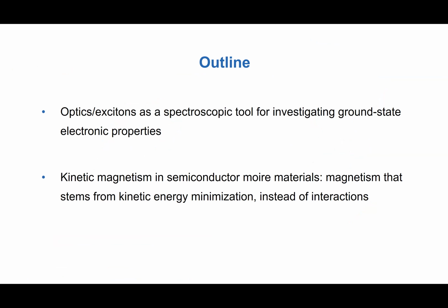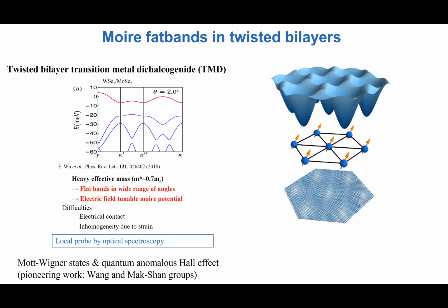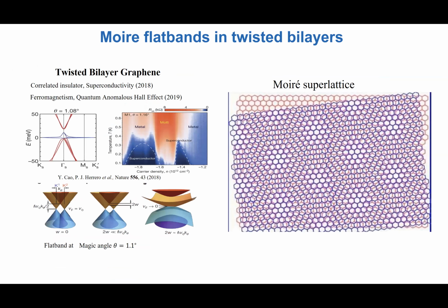Yes. Why is there no magic angle? Yeah, so basically, in the case of graphene, and there are experts here that can explain this much better than I do, but in the case of graphene, you start out with Dirac electrons, right? So this is as far away as you can get, in my opinion, from a flat band, right? So massless electrons. So what happens is that when you place two layers, and as they hybridize, they open up a gap, and the effect of this is to reduce the Dirac velocity down to zero, but this happens only at specific angles, okay? And only when the Dirac velocity goes to zero or around that point, you have these flat bands.